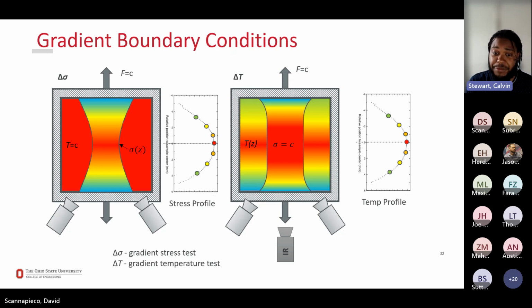Now, if you use digital image correlation, which is able to track the strains on the surface of a part, then you're able to extract creep curves, an infinite number of creep curves along the profile of that sample. So from one sample, one test, you get an infinite number of tests, depending on how much focusing optics you have, depending on how much zoom you got on your camera. Now, in the delta T test, you have a uniform sample, so you have a constant stress, but you adjust the temperature gradient. So you adjust the temperature field around that sample. And then if you have an infrared camera and you have your DIC optical cameras, you're able to measure temperature along that profile. And each of those points at different temperatures, again, represent a different curve, a different test. Stress and temperature gives you a different curve in different combinations.